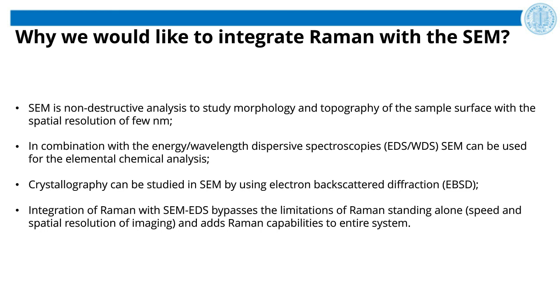Well, integration of Raman with SEM-EDS bypasses the limitations of Raman standing alone. The speed and spatial resolution can be improved, and on top of that, it adds Raman capabilities to the entire system. However, such integration is not flawless. The biggest difficulty is due to the fact that SEM is an electron beam-based technique, whereas Raman is light-based. Bringing the light to the SEM and collecting the weak Raman response from materials is very complicated technically, and it is not always simple to use. That means that in the majority of experiments, we don't need integrated systems, and it is probably easier to use two different standalone systems.